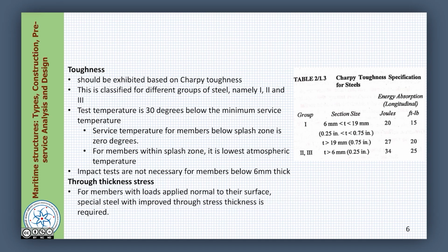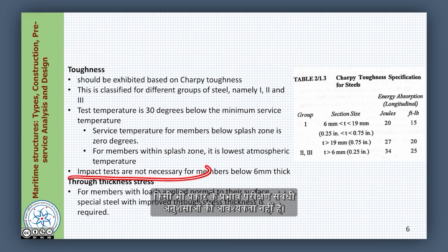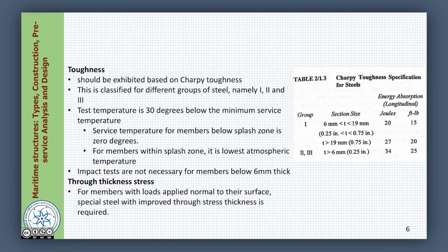So, you must conduct Charpy's test at 30 degrees below that minimum service temperature, because Charpy's impact index varies with the temperature at which the experiments are conducted. Friends, very important point here. If you are using a member whose thickness is less than 6 millimeter, you do not require any impact test recommendations at all. Any member whose thickness is less than 6 millimeter, no impact test requirement is suggested by the code.